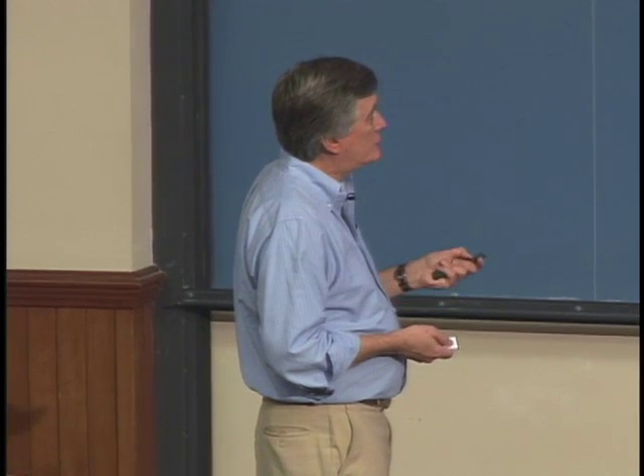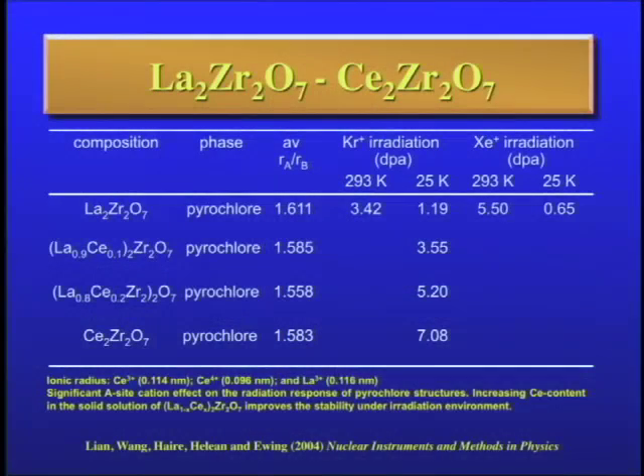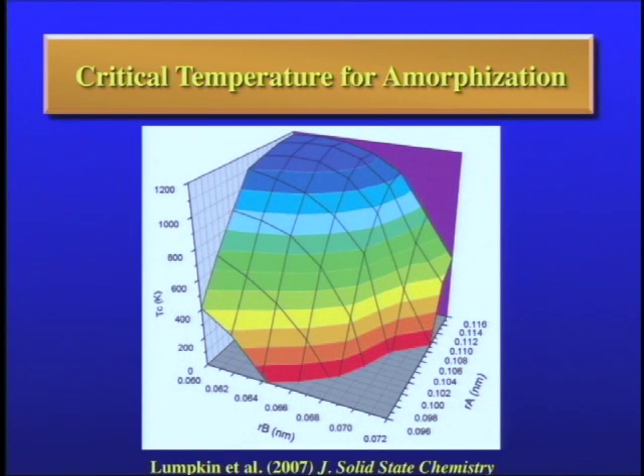And so we and others did a lot of experiments. If we start with the lanthanum zirconate, which could be amorphized at 25 K, okay, and substituted cerium, then you could see the dose increase. So literally there was a decade of work with everyone imagining or creating new compositions and generating the data from the ion beam experiments. And it can be summarized in a three-dimensional diagram where you have the size of the B site cations, the size of the A site cations, and this surface is that critical temperature. That is where the curves bend upward.